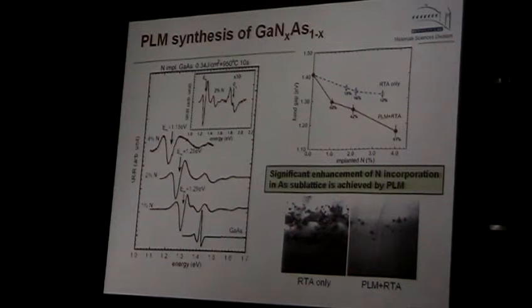And this shows gallium nitride arsenide. We synthesize it by this method. So we see that when we have gallium arsenide, this is energy gap of 1.4. This feature in photomodulated reflection says where there is a gap. When we implant nitrogen, 1% nitrogen, our gap shifts down. This is as expected because the band gap is decreasing, and this shifts even more. And by this method, we can really activate about half of the nitrogen we are putting here.